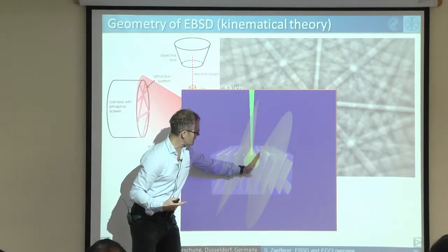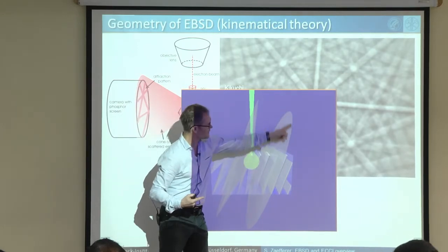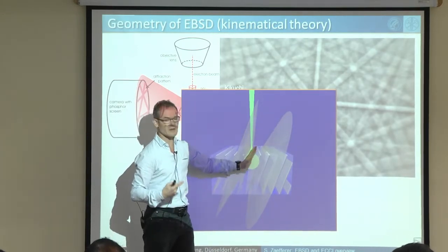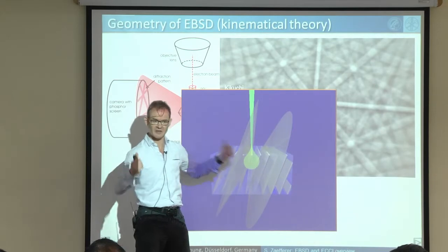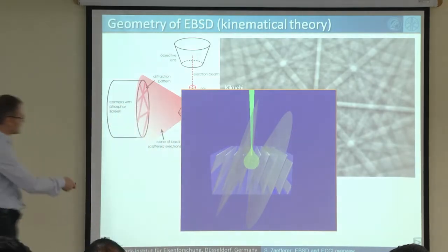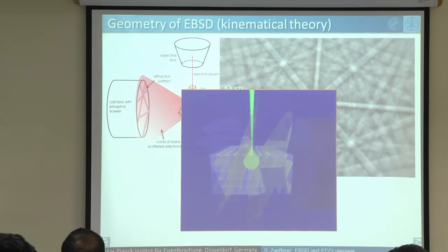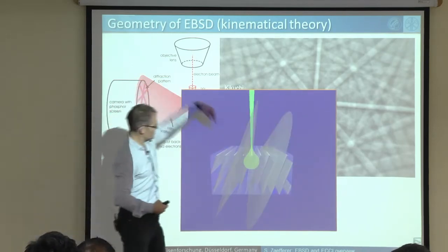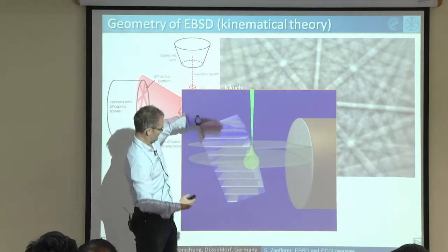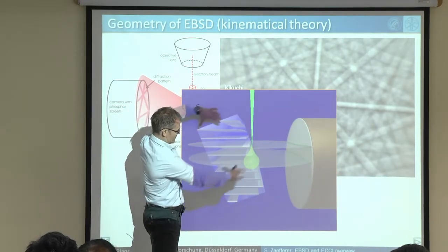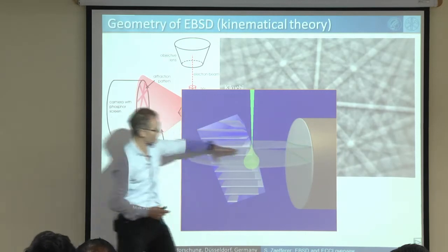If the electrons travel on these cones, they all have the same angle with the lattice planes, actually the Bragg angle. Good. So we find that these two cones, one forward and one backward cone, are the areas where electrons travel under the Bragg angle with respect to these lattice planes. And now, in order to do EBSD, we are tilting the whole setup. So instead of looking in transmission, we are looking in reflection. So still the same thing. The lattice plane, the crystal has been changed now, and the cones are now traveling in this direction.